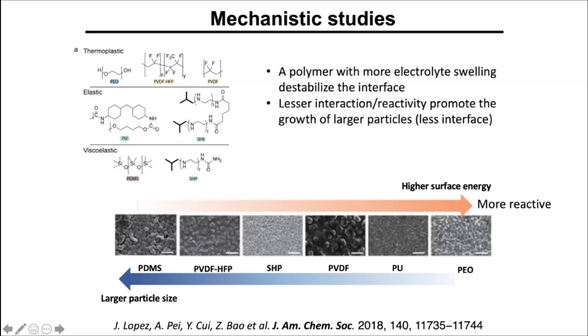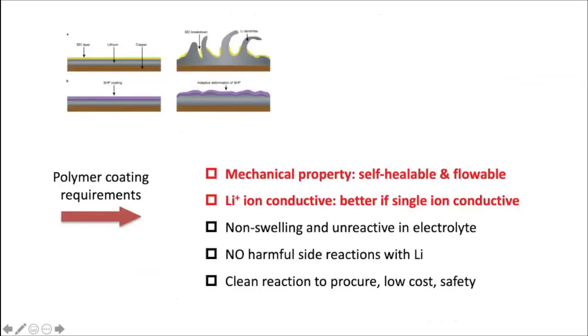that led us to conclude that for the desirable coating, we should keep the self-healing and flowable property that comes from the dynamic nature of the polymer we design. This will be desirable for addressing the mechanical instability in the coating, and also the mechanical instability in the lithium metal anode.